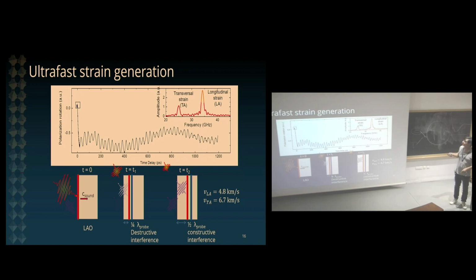And you see that if you take the Fourier transform of this oscillation, we actually see the propagation of two modes. From the position of this peak, you can actually measure the speed of sound. This mode here corresponds to the longitudinal speed of sound of lanthanum aluminate, which is 4.8 kilometers per second. And this peak here corresponds to the transversal speed of sound, which is 6.7 kilometers per second, which matches the literature perfectly.